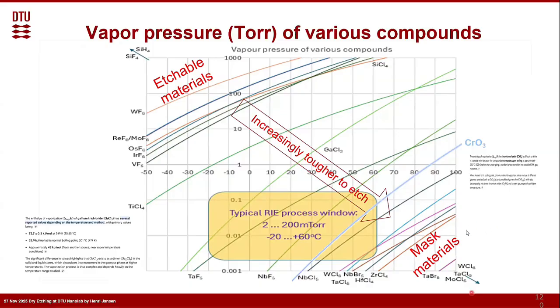So the lines passing here will be materials which, under that condition, are not going to be etchable. For tantalum, if you would try to etch it with bromine, it means it will not work. For molybdenum, the same, it will not work. But it doesn't mean that you cannot etch tantalum, because we see here it passes the line when we have tantalum pentafluoride. And this is now the interesting part.